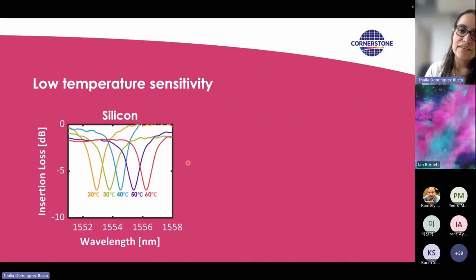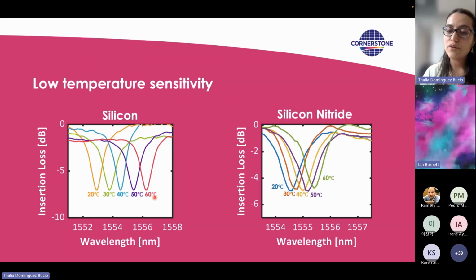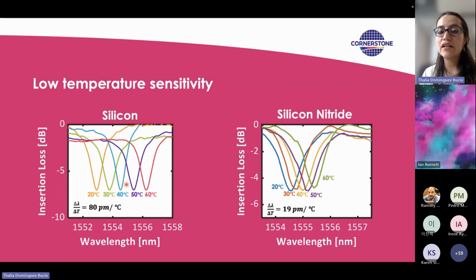The other thing, as I mentioned, is that it's less sensitive to temperature variations. So we look here at the response of a standard silicon ring resonator. You will see that if we change the temperature from 20 to 60 degrees, the shift of the central wavelength is quite big. If we do the same with silicon nitride, you will see that the change is much smaller. So we're seeing that the sensitivity of silicon is around 80 picometers per degree centigrade compared to silicon nitride that only has 19 picometers per degree centigrade, which means that silicon nitride is more stable to temperature variations.